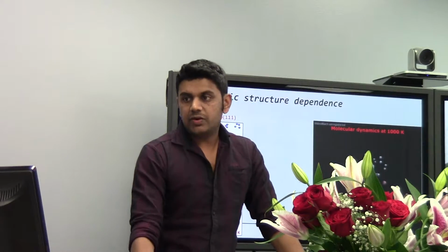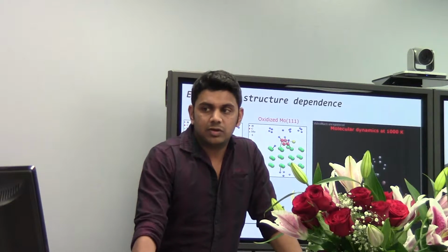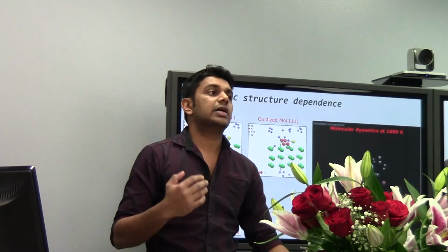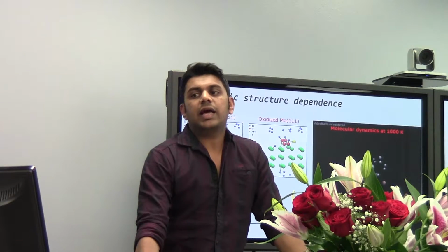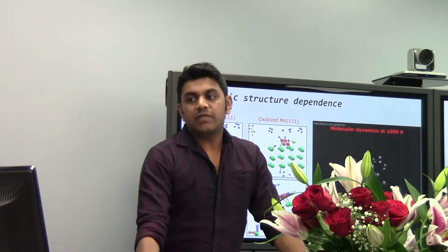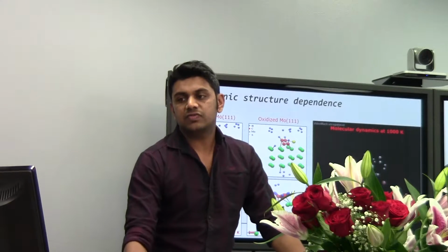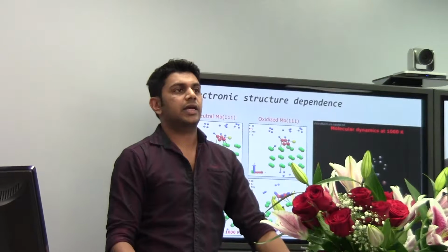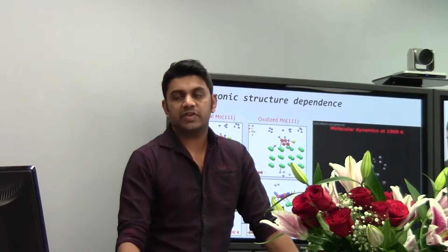And we also did, so here you can see thiophene molecule adsorbed on oxidized molybdenum surface, moderately oxidized molybdenum surface. So at 0 Kelvin, like in the neutral molybdenum surface, only one carbon-sulfur bond is broken. So when the surface temperature is increased to 1000 Kelvin, there are evidences of dissociating both carbon-sulfur bonds. That means it seems like oxidized molybdenum surfaces are catalytically active towards the hydrodesulfurization reaction.